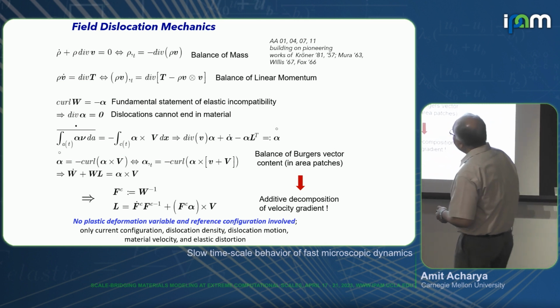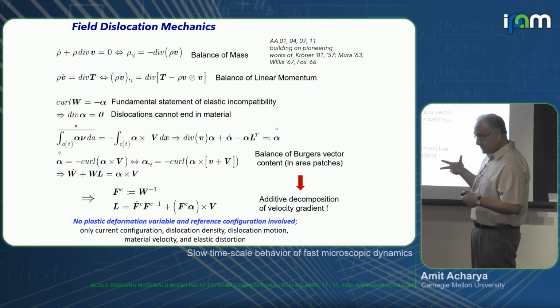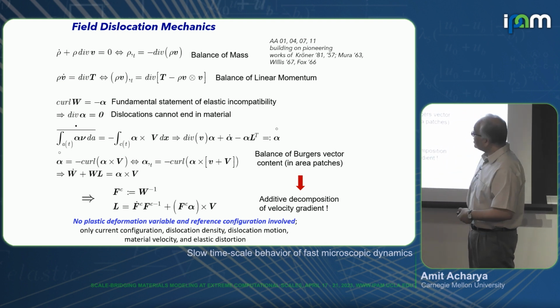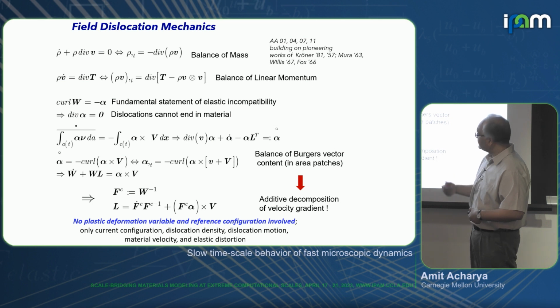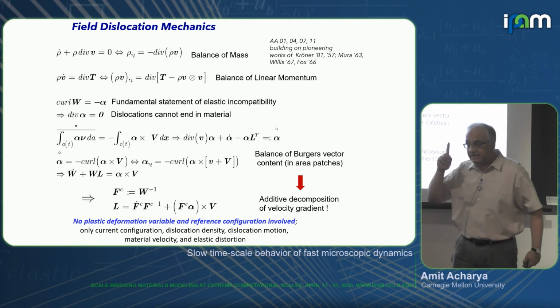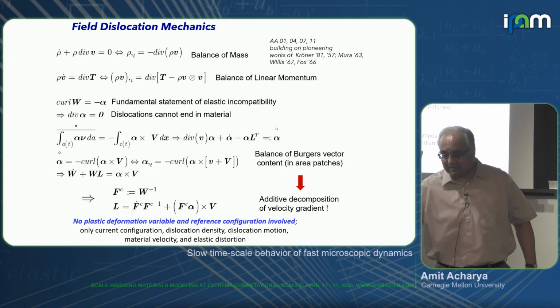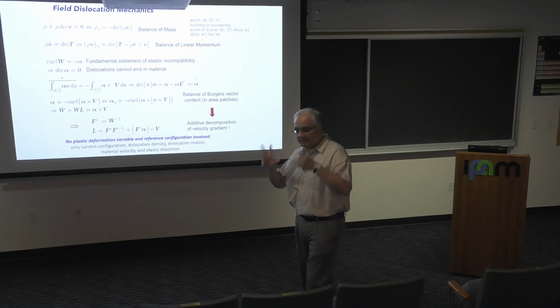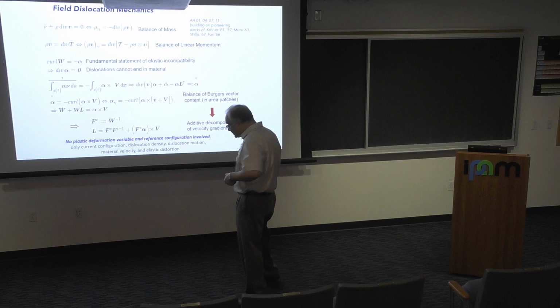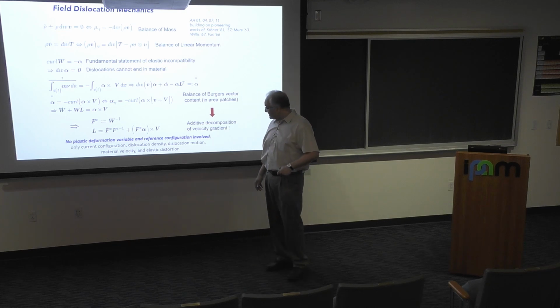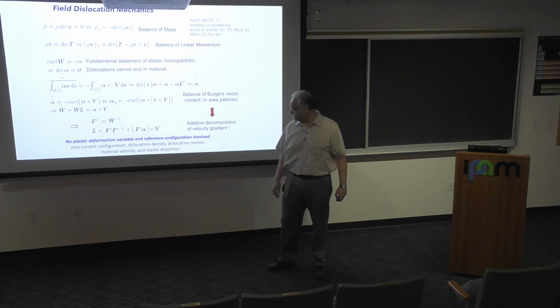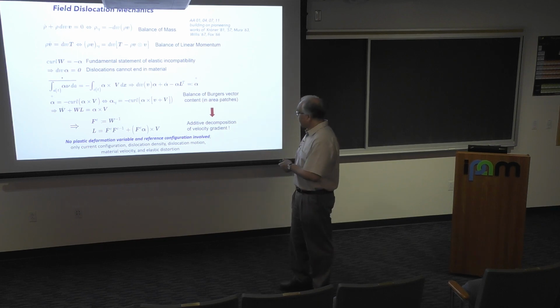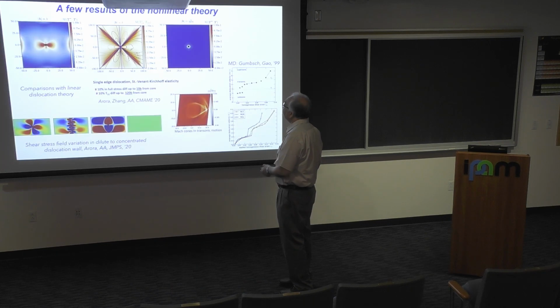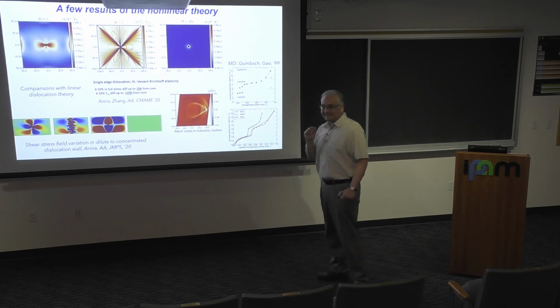Okay. So that's that. And a consequence of this in this model is this Burgers vector conservation. If you localize this and look at an equation for W, it will come out this way. This is, by the way, the flux of dislocations. And you just manipulate this. And the additive strain rate decomposition is not an assumption here. You don't have to say multiplicative, additive, and play with that. Burgers vector conservation tells you it is just this. So this is the elastic strain rate, this is the plastic strain rate, the total is this, all right? It just falls out. Okay, that is the PDE structure. Keep this in mind. Well, sure, keep this in mind, but that's what we'll play with.